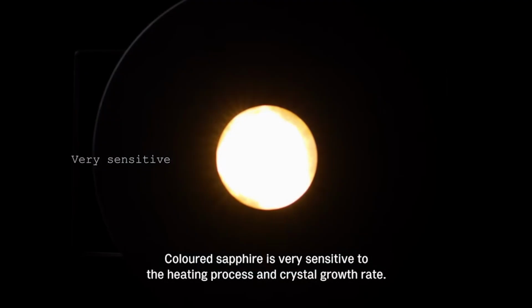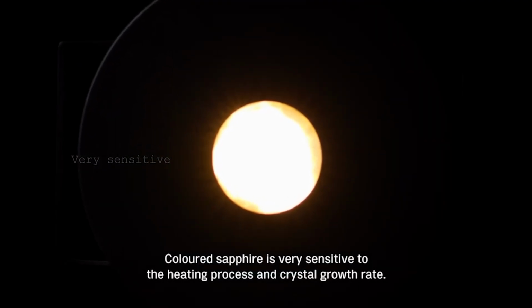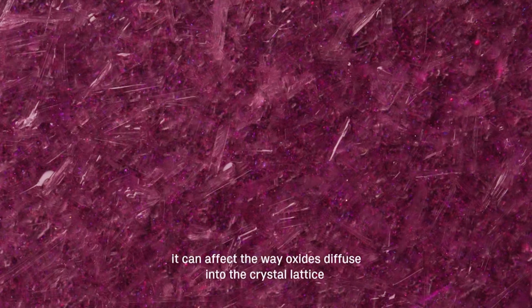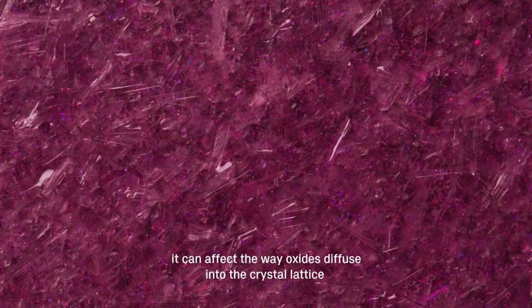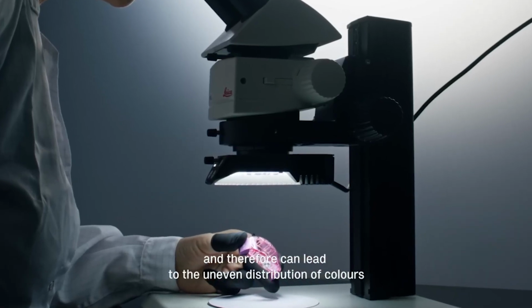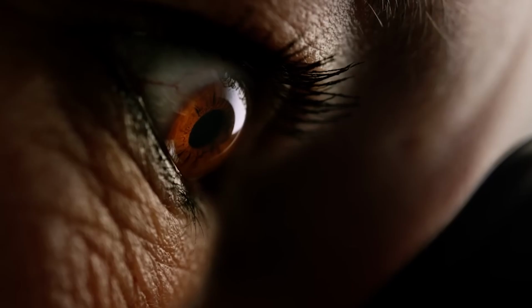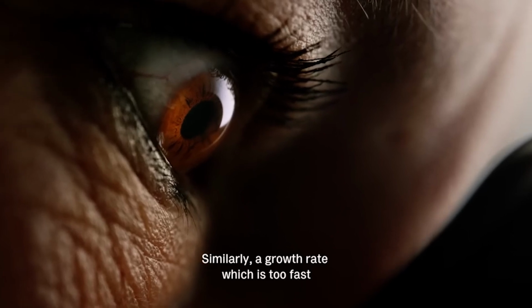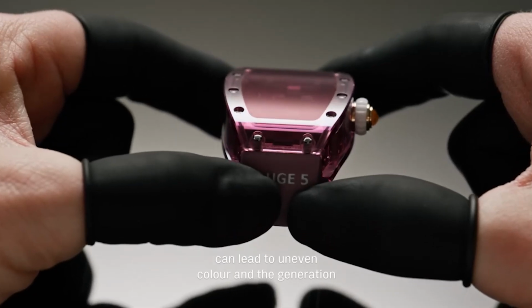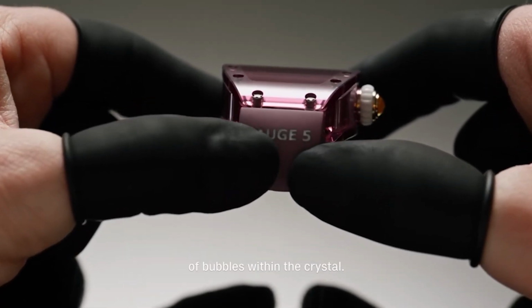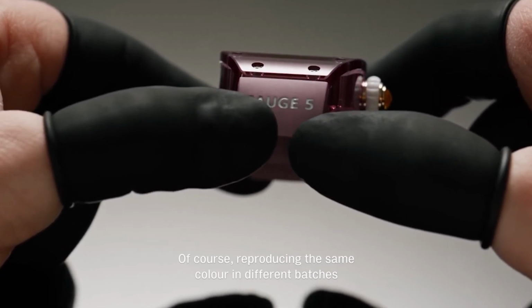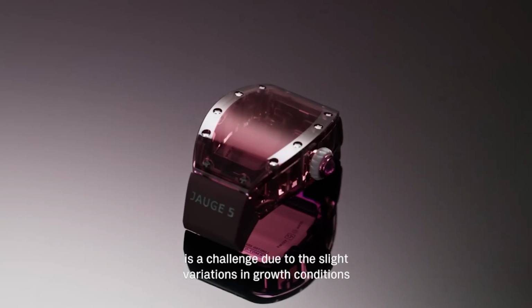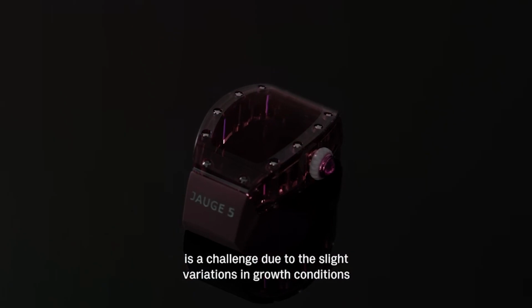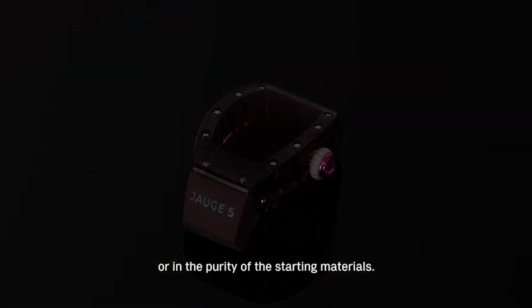Coloured sapphire is very sensitive to the heating process and crystal growth rate. If the right temperature conditions are not respected, it can affect the way oxides diffuse into the crystal lattice, and therefore can lead to the uneven distribution of colours or undesired hues. Similarly, a growth rate which is too fast can lead to uneven colour and the generation of bubbles within the crystal. Of course, reproducing the same colour in different batches is a challenge due to slight variations in growth conditions or in the purity of the starting materials.